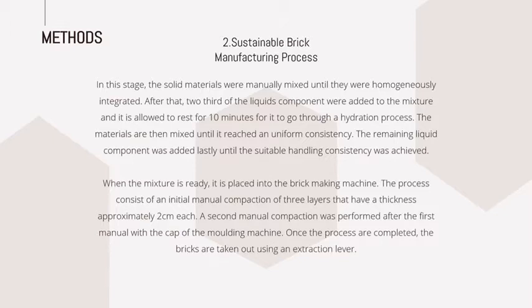were homogeneously integrated. After that, 2/3 of the liquid components were added to the mixture and it was allowed to rest for 10 minutes to go through a hydration process. The materials are then mixed until they reach uniform consistency. The remaining liquid component was added lastly until a suitable handling consistency was achieved. When the mixture is ready, it is placed into the brick making machine.